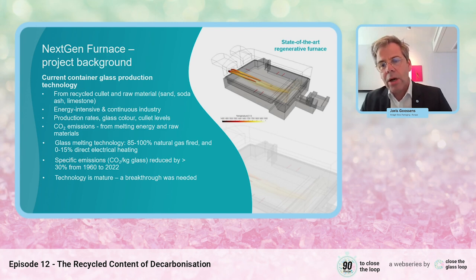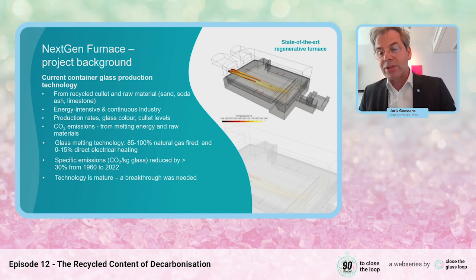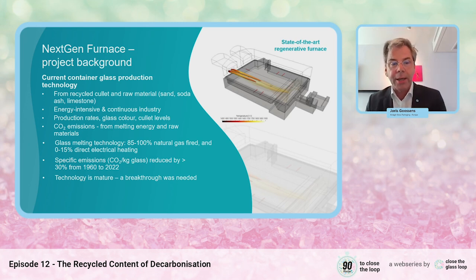And this technology is a very versatile technology. This type of furnace, which you see in this picture, is fit for different pull rates, production rates that is, different colors, different cullet levels. So it's a very versatile technology. And the CO2 emissions from this type of furnace come from both the melting energy and the raw materials which decompose. Some raw materials decompose and release CO2, soda ash, limestone, dolomite.